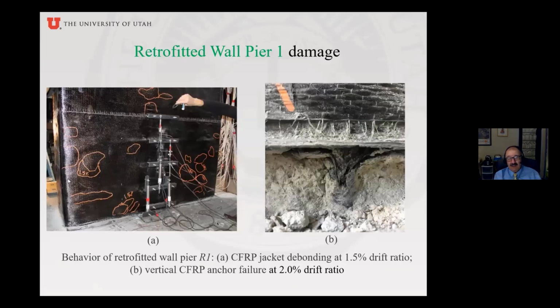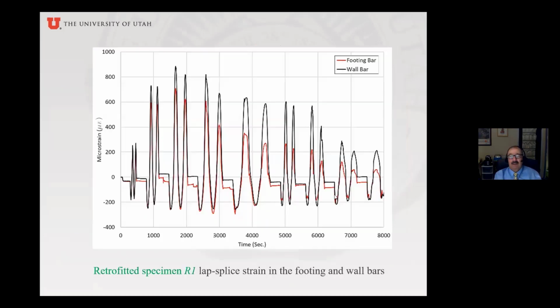And you can see here, of course, these are debonded areas, these little circles that you see where we hit it with a quarter or a washer, we can hear it's hollow. That means the carbon fiber is debonding from the concrete. But here is the main failure, which, as you saw, the anchor here failed at about 2% drift ratio. One of the anchors, it actually failed.